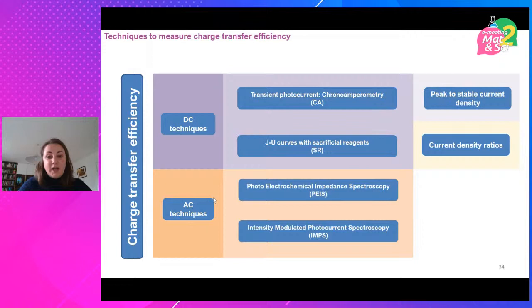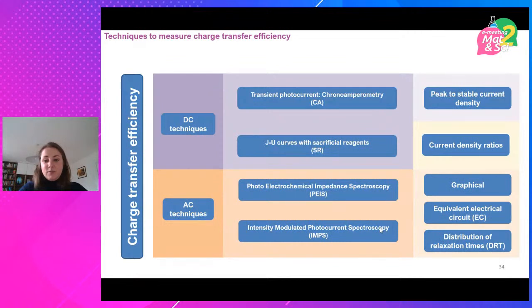And then the stuff that's a little bit out of my area of expertise, because I've never actually personally done these experiments or the analysis. In terms of AC techniques, we've got photoelectrochemical impedance spectroscopy, which is the same as normal electrochemical impedance spectroscopy, but when you shine light. And then Frankie did intensity modulated photocurrent spectroscopy. And he did all kinds of different analyses on this system. So not just equivalent circuit fitting, which is what you can do if you want to avoid this use of single frequencies for Mott-Schottky, but also things like distribution of relaxation times, which is something that he discussed a lot with his collaborator Dino Klotz.